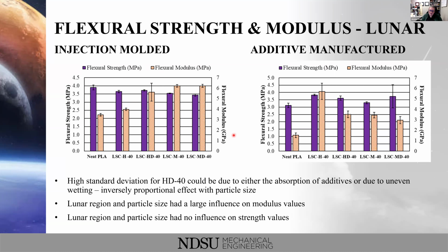We're not really sure, we've got to do some more experimentation into this. This was an effect that we saw in additive manufacturing as well with some of our parts, which I think, with the Highlands, might just be part of the additive manufacturing process. But the Mare dust, again, showed a really high standard deviation when it came to our flexural strength. Our lunar region and the particle size, in this case, had absolutely no impact on the strength values for additive manufacturing. Which is really promising to see.